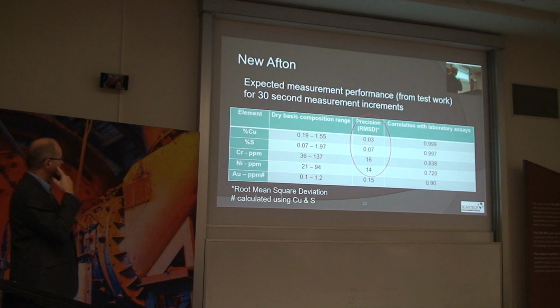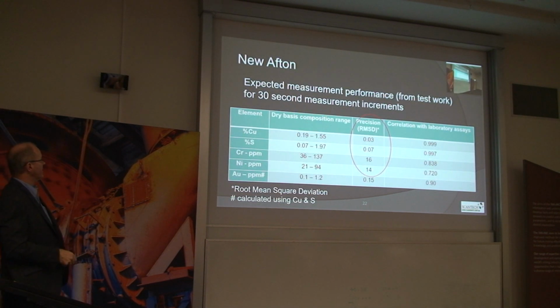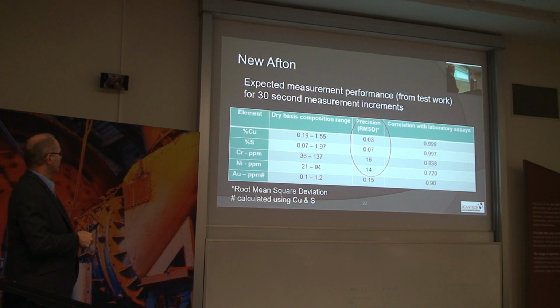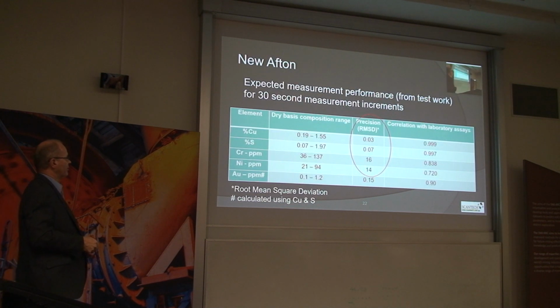And these are the accuracies we achieved from that test work. For that range of copper, we achieved a measurement accuracy of 0.03% copper. That's the correlation between the lab and the analyzer results. For sulphur, accuracy 0.07% sulphur. Chromium, these are in ppm. So they're the ranges of chromium and nickel, and the accuracies for measuring those around 15 ppm.